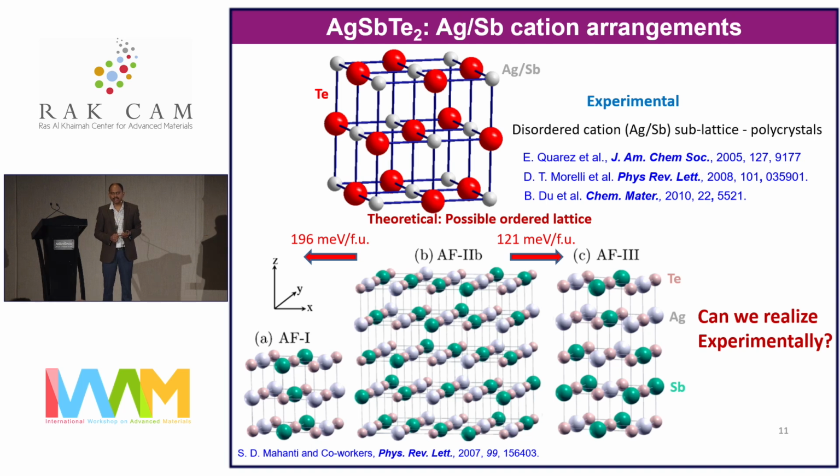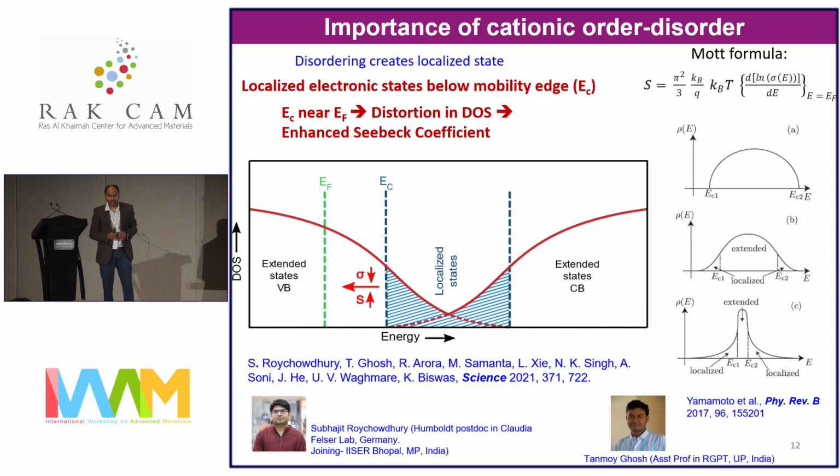In a non-interacting system, if the charge carrier mean free path matches the interatomic distances, the material's electrical conductivity can go to the minimum, which is called the Mott-Ioffe-Regel limit. Now, in a three-dimensional system, if we have a critical level of disorder in the solid, the system can become an insulator, which is called the Anderson insulator. The material can go from metal to insulator.